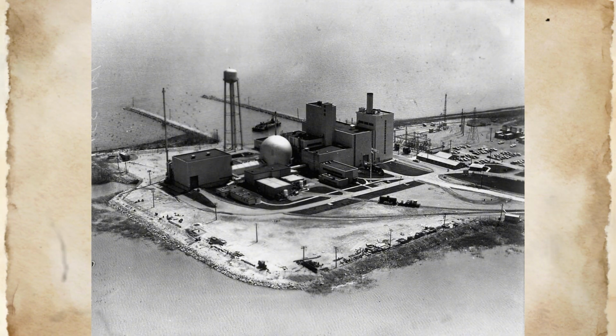Noble gas fission products such as xenon and krypton isotopes were detected in concentrations well above normal background levels, providing quantitative evidence of the extent of fuel damage that had occurred. The isotopic signatures in the cover gas samples would eventually allow investigators to estimate the number of fuel pins that had been damaged and the approximate time frame over which the damage had occurred.